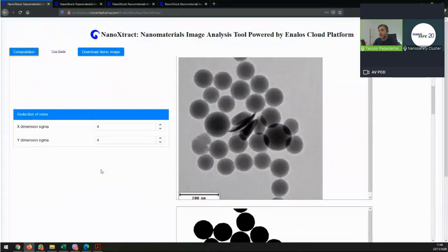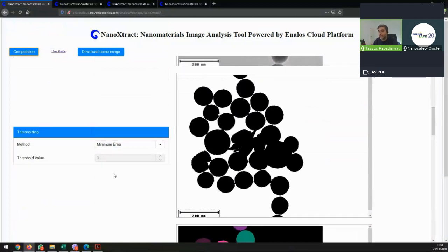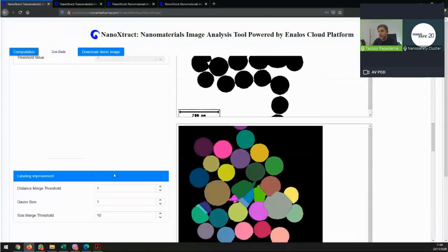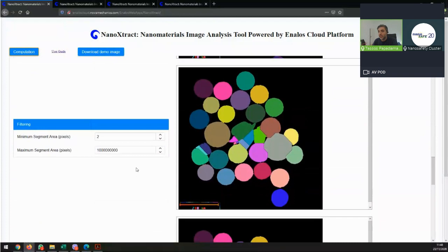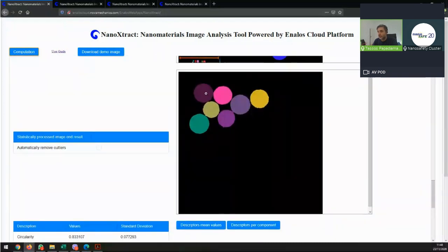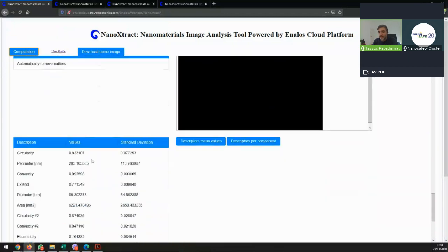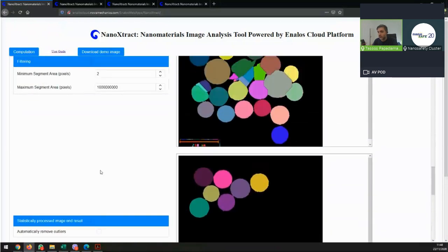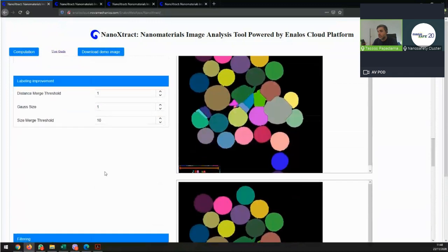So here you can see now that we have a pretty good, clean inverse of the image. You can see here that it identifies things. Here is the part that's the most problematic, and eventually we get, let's say, a part of the images of the particles here. It's an estimated diameter of 86 nanometers. I don't know, Martin, if that fits well. So you see that it identified.